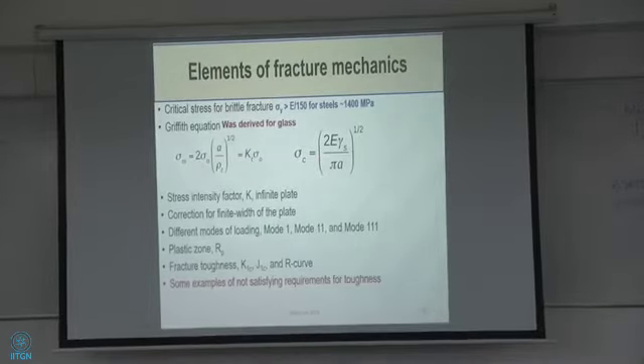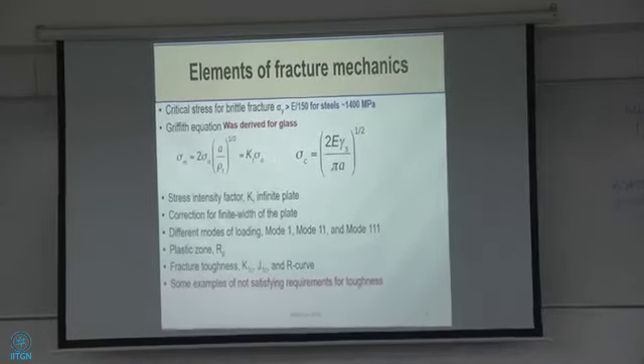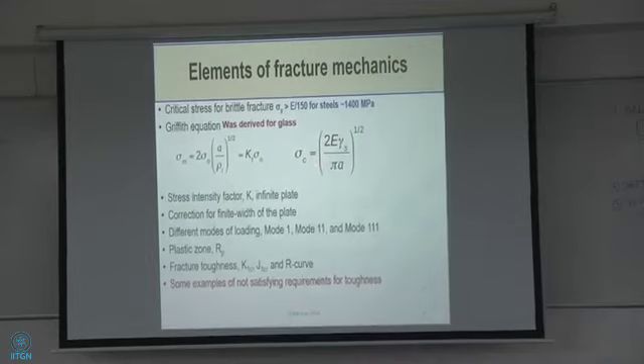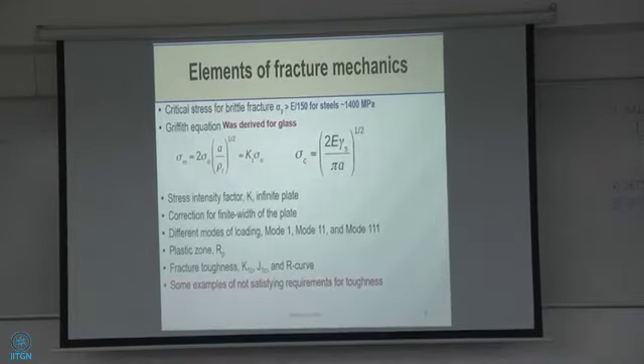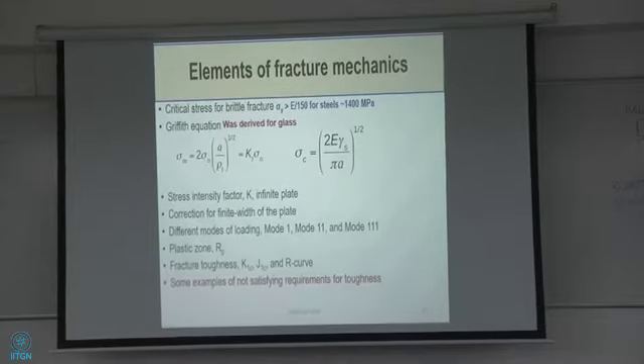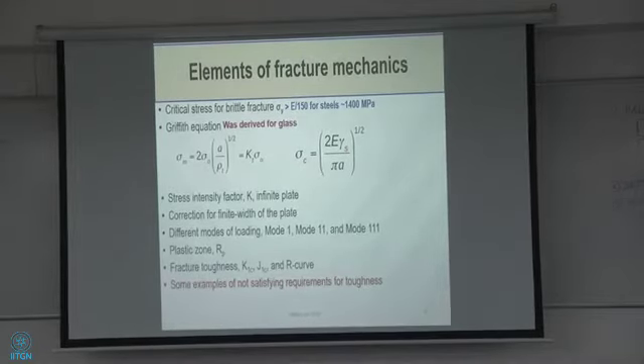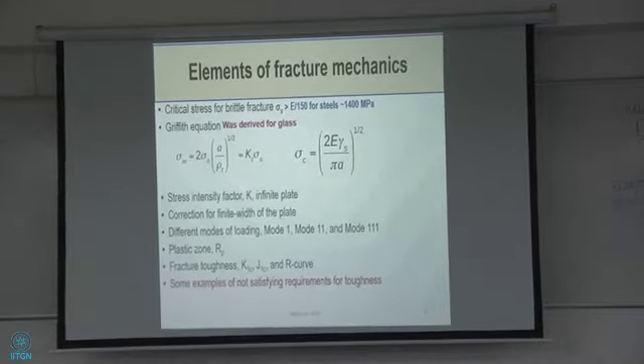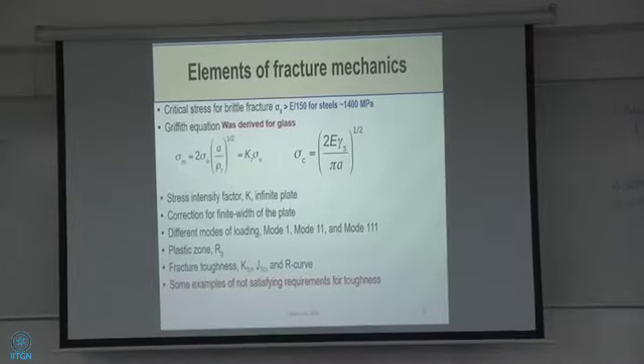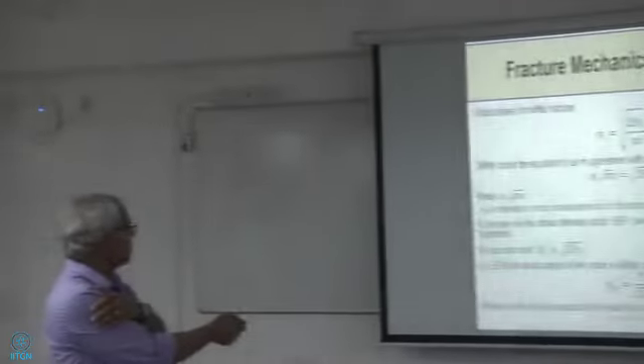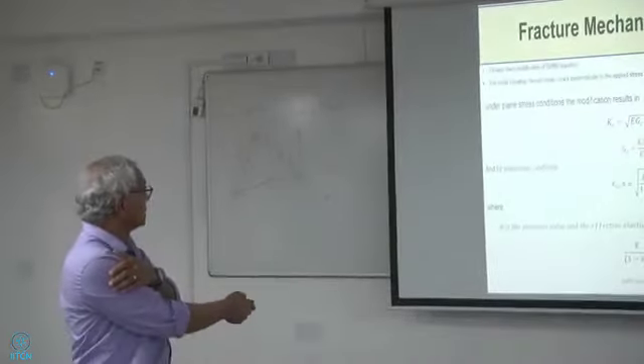The critical fracture stress to break the glass is a function of the elastic modulus of the material, surface energy, and the crack length. The length of the scratch that you put in. Purely based on a number of experiments on fitting the data, critical fracture stress.